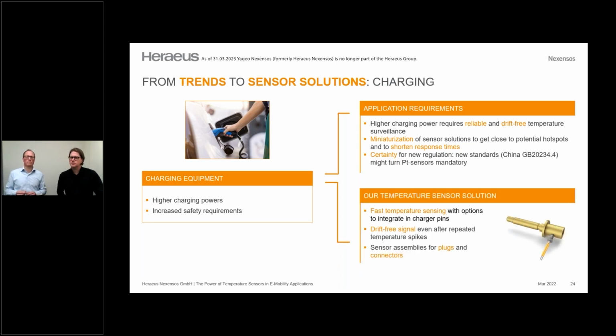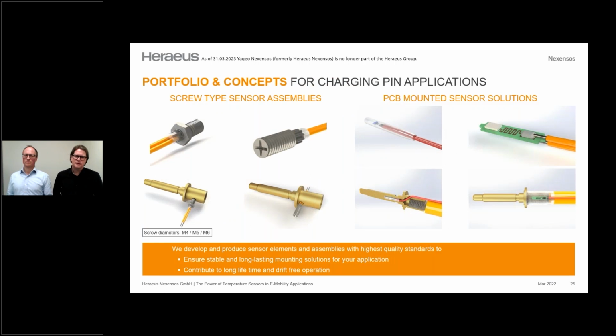Our temperature sensor solution stands for fast temperature sensing because we measure where the heat source is located. The drift-free signal is because of our basic physics behind it. That means the PT element is in general very stable against drift. And how we can assemble this to the plugs and connectors we see in the next slides. Here are some different ideas for mounting with screws. In the first two pictures, you can screw in directly in the metallized area of that pin, which leads to a very good heat transfer.